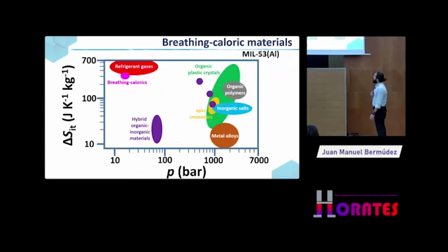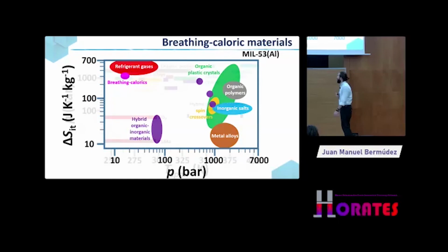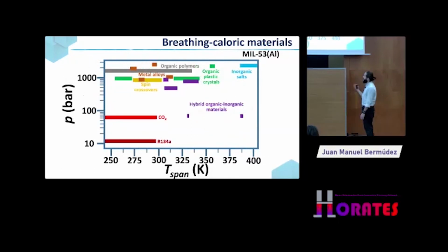So, for the first time, with those materials, we observed that we were here, so close to the refrigerant gases, 300 joules per Kelvin per kilogram, by using only 16 bars. So we were in the target of the refrigerant gases. And what about the operating temperature range? Well, in that case, we also observed very interestingly that we were able to operate the material in this temperature span. So we increased the temperature span of our material beyond that of the refrigerant gases.